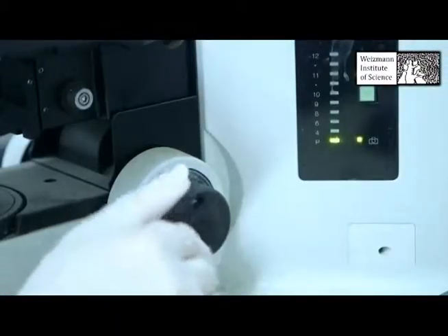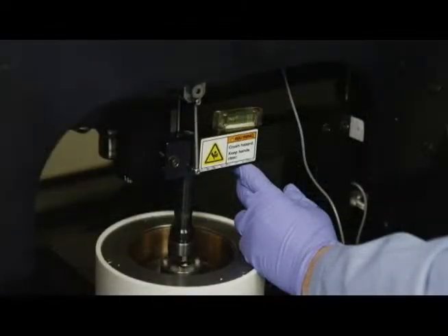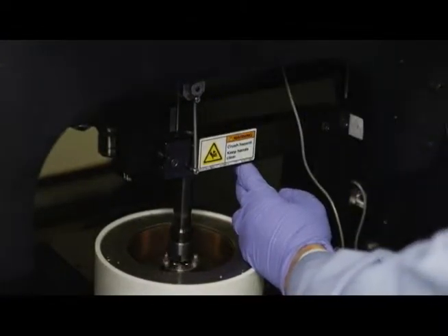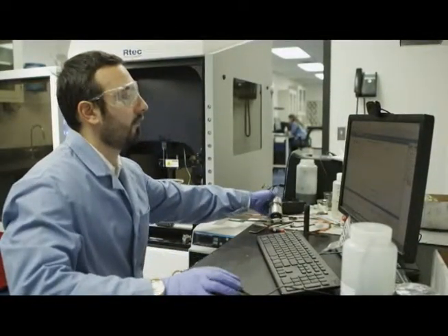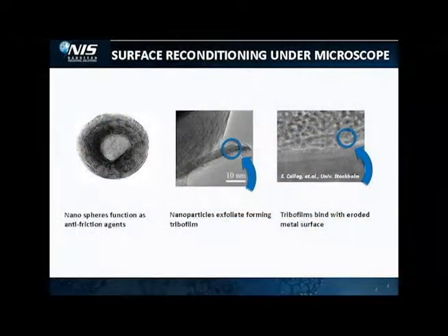At 20 to 200 billionths of a meter, nanoparticles are beyond small. The reactor and chemistry used to make the particles causes these tiny spheres to be hollow, with a multi-layered outer skin. Under extreme pressure conditions, the multi-layered skin begins to exfoliate, leaving tiny peels of tungsten disulfide that adhere to the metal surfaces, and create a film that reconditions and lubricates the metal while reducing wear.